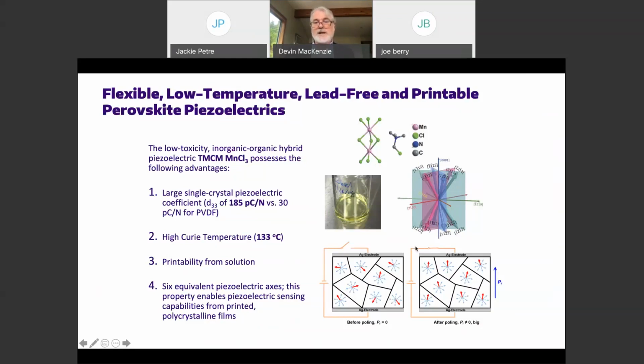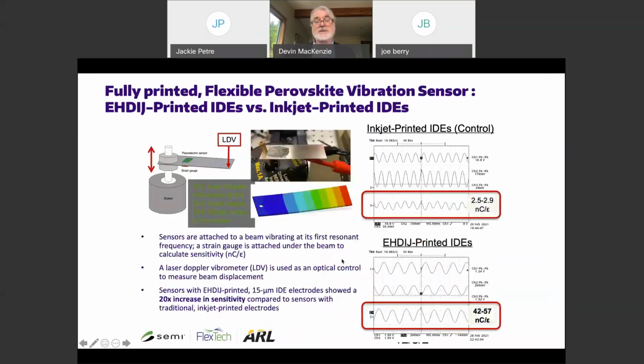So we developed this concept, developed the inks, and also developed a test structure for this. This is based on that ultra high resolution metal print and slot die coating of this piezoelectric perovskite to produce fully printed flexible perovskite vibration sensors. This would detect, say, missing rivets on an airplane wing or bullet holes in a fighter jet or something like that. We could actually pick up and even directionally identify the direction from which a vibration is coming with the correct sort of array of sensors.